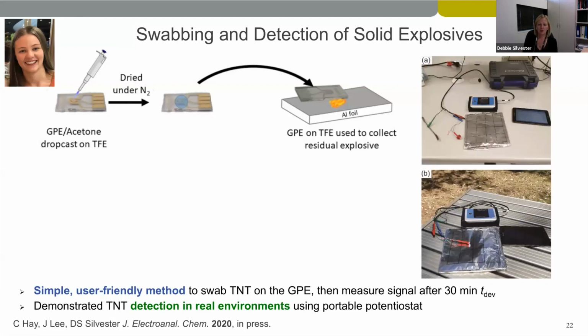Because we wanted to use this for forensic applications in the real world, Kathy did this in ambient conditions, so under no gas flow. We didn't try to remove any moisture. So you can see the experimental setup where we have the aluminium foil and the electrode, and then we have a handheld portable potentiostat. And at the bottom, we have the same handheld device taken outside. This was actually done on a 36 Celsius day, so it was quite a hot day at the time.